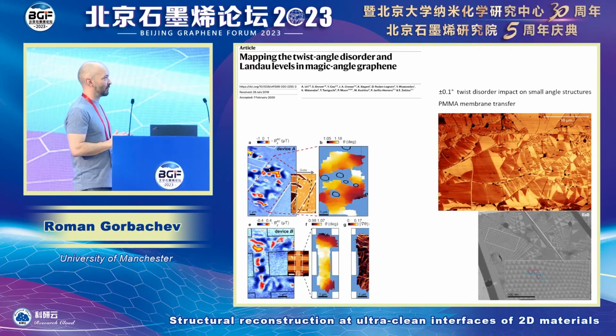Now, what is the problem? So the problem is, of course, twist angle, because if you go and make a twisted device in a lab, you will probably see something like this. You will see a lot of cracks, a lot of bubbles, and really you cannot move on with this into applications until you solve the problem of homogeneity. And this is why the bubbles and the cracks and the transfer technique is really the key to progressing these high-end optical and electronic applications.